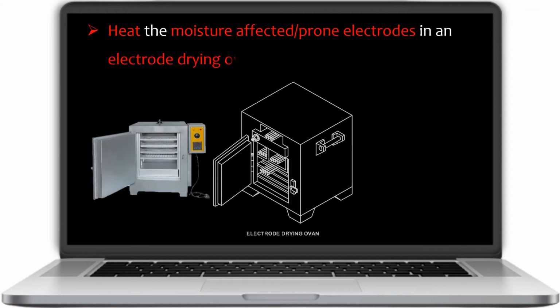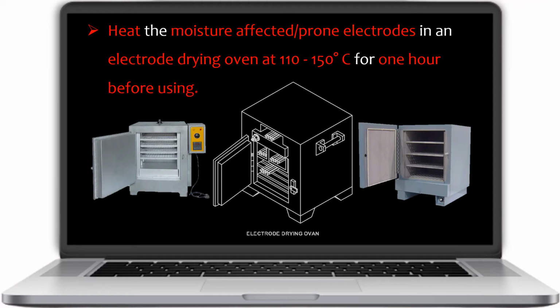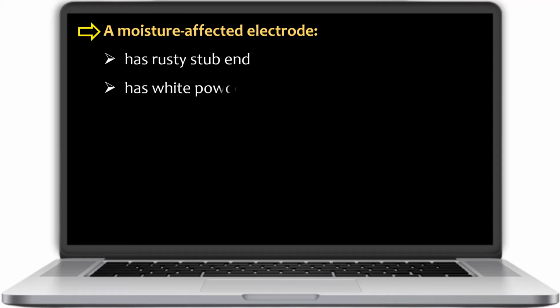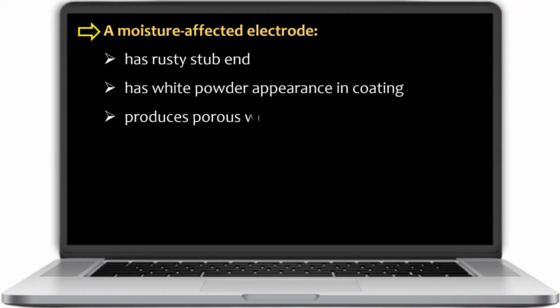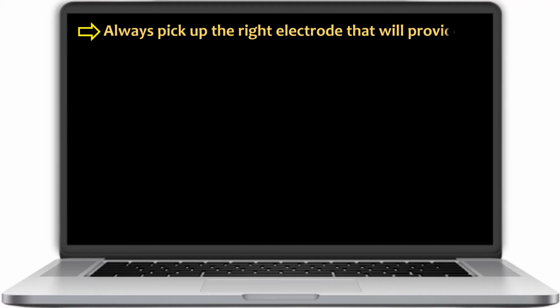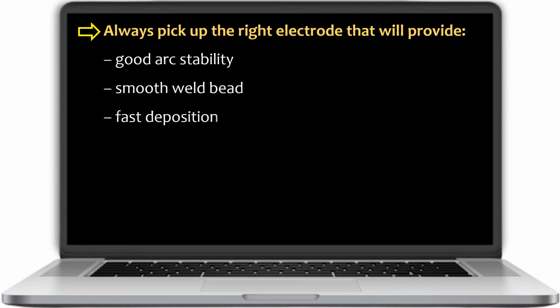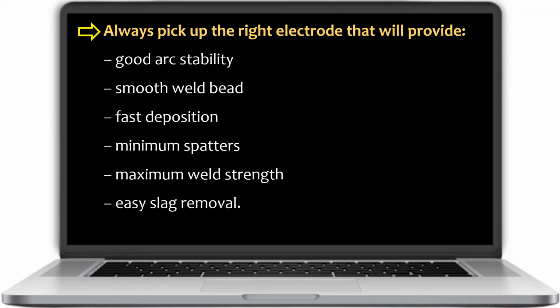Heat the moisture affected or prone electrodes in an electrode drying oven at 110 to 150 degrees Celsius for 1 hour before using. Let's see how the moisture-affected electrode will be. A moisture-affected electrode has rusty stub end, has white powder appearance in coating, produces porous weld. Always pick up the right electrode that will provide good arc stability, smooth weld bead, fast deposition, minimum spatters, maximum weld strength, easy slag removal.